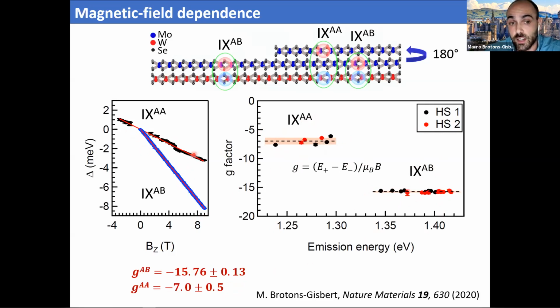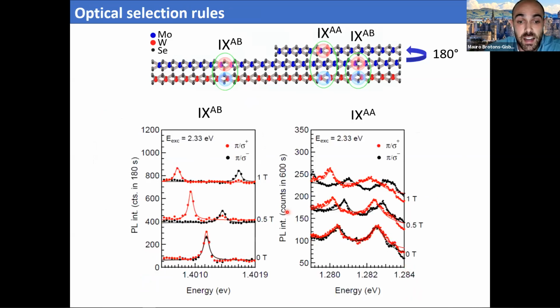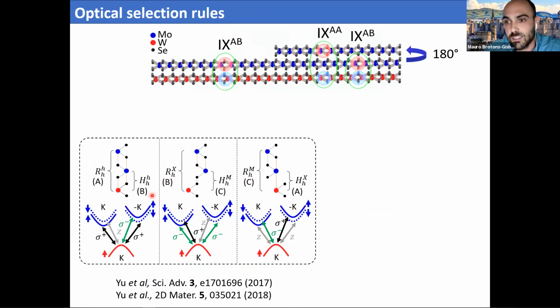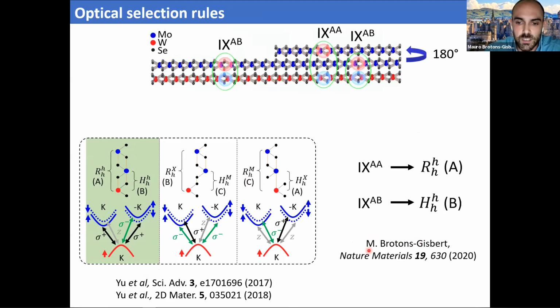So these G factors can be very well understood just by the spin and the orbital involved in the bands, okay? You can have a look in this recent paper where we have explained this in more detail. And combining these magnetic field results with the optical selection rules that we measured, we can conclude that the atomic sites responsible for trapping the excitons have this particular atomic registry. Okay, so again, I went a bit fast in this part, but you can have a look in this paper that we've recently published.